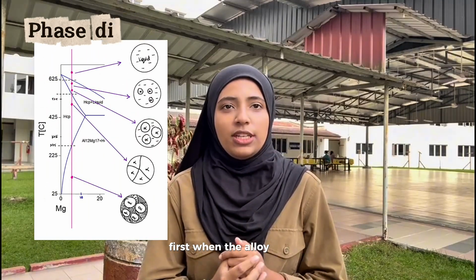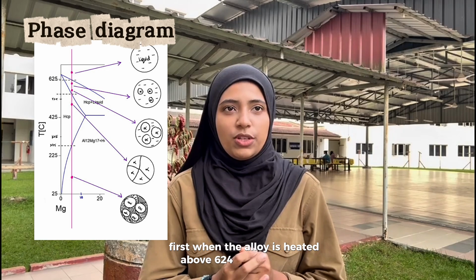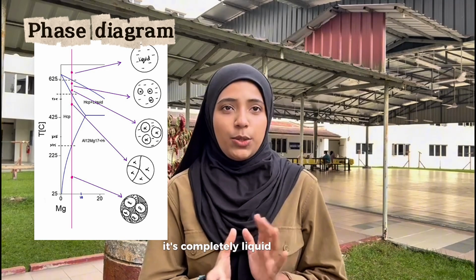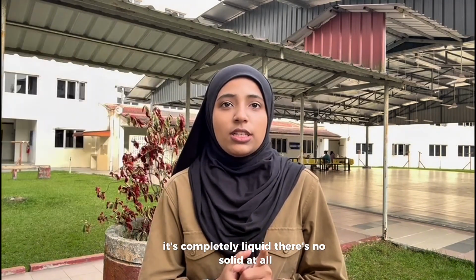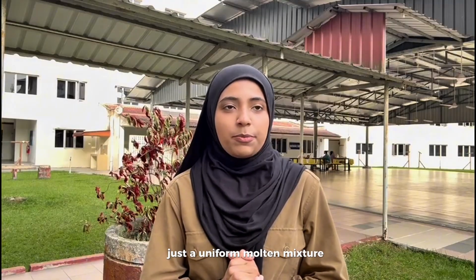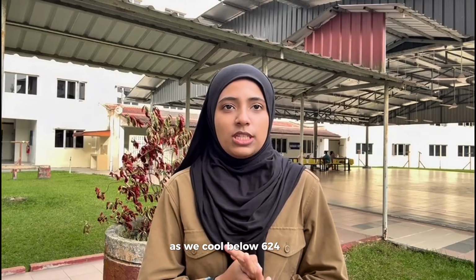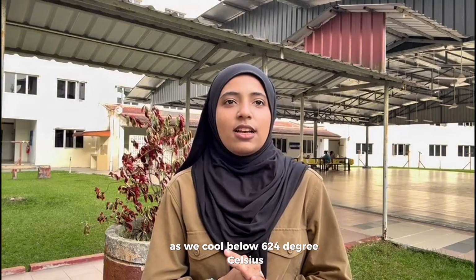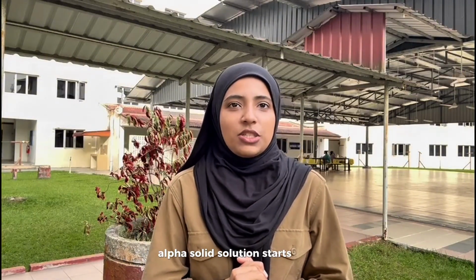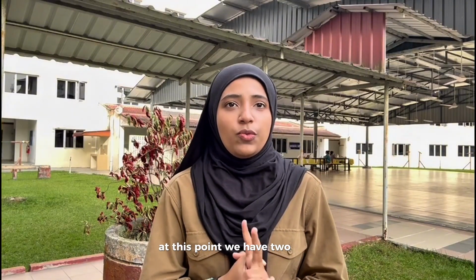Today I'm going to walk you through the phase transformation of a magnesium aluminium alloy, specifically one with 5% aluminium and 95% magnesium, as it cools down from a completely liquid state to room temperature. First, when the alloy is heated above 624 degrees Celsius, it's completely liquid. There's no solid at all, just a uniform molten mixture. As we cool below 624 degrees Celsius, alpha solid solution starts to form. At this point, we have two phases coexisting, solid and liquid.